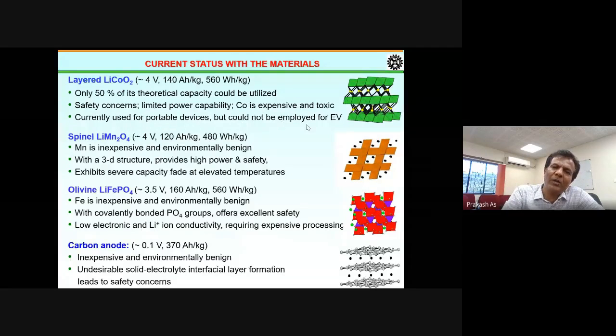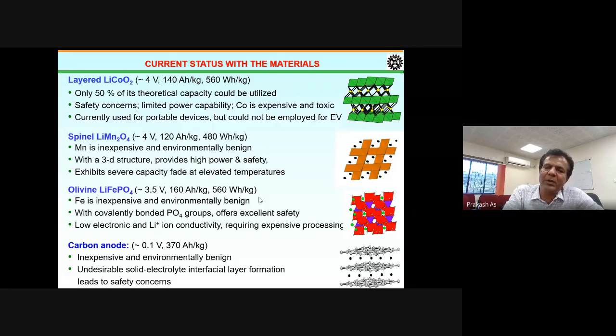And spinel LMO is also a 4-volt lithium manganese oxide, and the capacity is 120 ampere hour per kg, and volumetric is 480 watt hour per kg. Manganese is very cheap, inexpensive, environmentally benign, and safe. With the 3D structure, it provides high power as well as safety, but however, it has a severe capacity degradation. If you are targeting some application with 200 cycles or 250 or 300 cycles, then you can use it. If it is for longer cycle life, it is not good, because in every cycle there is a decay in the capacity and so on.